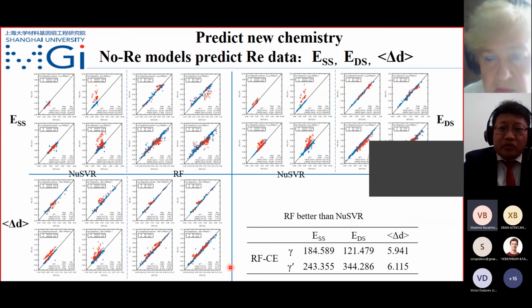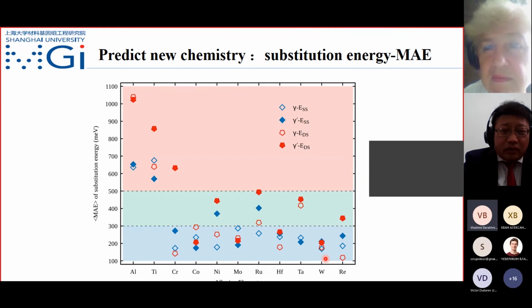We also try another thing. We want to try to predict new chemistry or new alloy elements, because that's important for new alloy design. For example, we train the data without the ruthenium, and then we predict with the ruthenium, to see how our model works. And it turns out the error is much larger. In this case, we go to 180 milli eV, much larger than the previous one, which had a random split of the data. So that means if we predict a completely new element, one not seen before in the training, then the prediction is not very good. It is worse than if it was there. Okay. And we compare using the leave-one-out method for each new element, and this is the result.